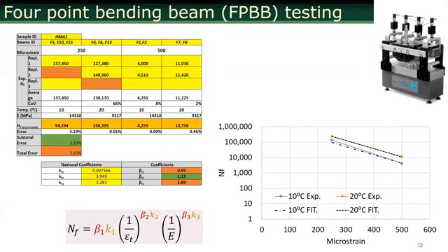So along those lines, on the creep compliance, I noticed the temperatures were very low, and they were 18 degrees apart. Yeah. Again, no significance to that. I mean, who decides? That particular one does have an AASHTO standard, and it clearly says minus 20, minus 10, and 0 degrees Celsius. So 10 degrees Celsius difference. There's an AASHTO standard that you have to follow to come up with the creep compliance. Minus 4, 14, and 32. It's 18 degrees apart. That's Fahrenheit. Yeah. So it's 10 degrees Celsius difference.